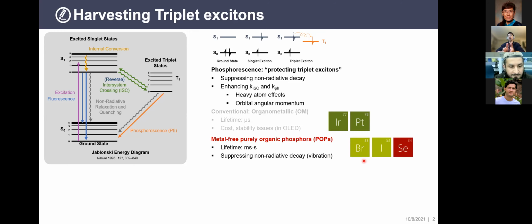So our group is very interested in developing so-called metal-free, purely organic phosphors, and that's where this word POP comes from. We do need some heavy atom, and instead of using a metal, we use organic derivatives of heavy atoms, which are usually bromine, iodine, or, recently in our group, selenium. Because they are not that heavy, the lifetime of our phosphorescence materials is usually in the millisecond, even to the second regime.